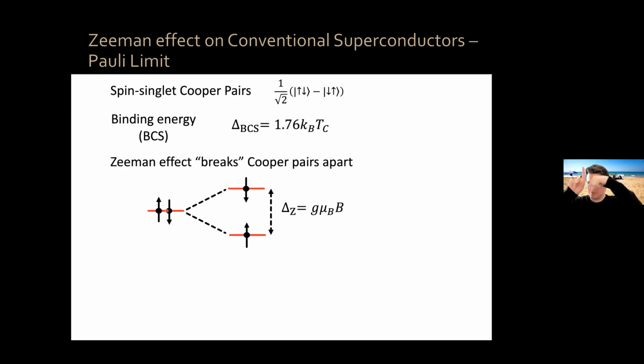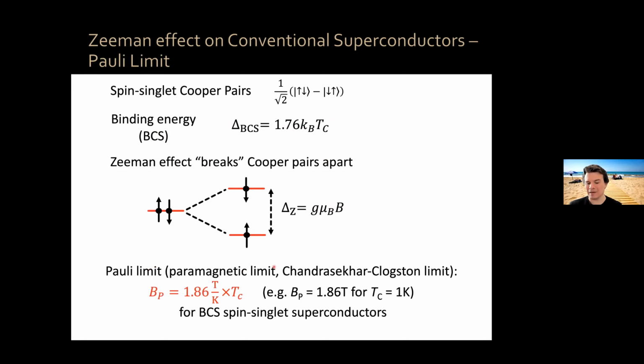So there is a limit called the Pauli limit, or the paramagnetic limit, or the Chandrasekhar-Clogston limit, where essentially once your Zeeman splitting is equal to the binding energy of your Cooper pairs, you just break your Cooper pairs apart, okay? So that tells you that for a conventional superconductor, you expect to kill superconductivity due to Zeeman effects at a critical field of about 1.86 times your critical temperature, okay? So for a critical temperature of 1 Kelvin, you expect your critical Pauli field to be 1.86 Tesla. That's for BCS spin singlet superconductors, okay?